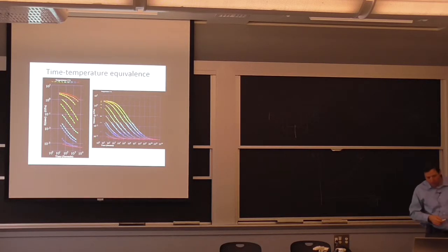So what people do with this is essentially accelerate the testing, where you have different experiments. You can do it here, for example, at different temperatures, but for a short period of time, something that you can do here within a few hours. And use that data to generate what would happen over time if I had run the experiment much longer. It's a very nice process of analysis. It is based on the same viscous process continuing for all these conditions.